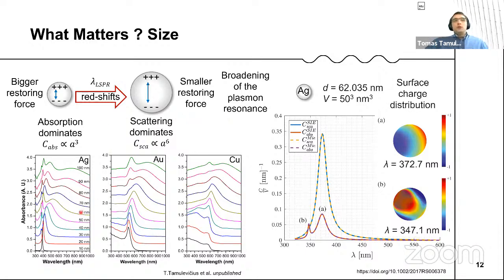And here are some numerical simulations with Mie theory for silver, gold, and copper. You will see why, because we had a small project about it. If we increase the size of the sphere, you can see that the dipole peak is shifting to longer wavelengths, and it's really broadening, as I just said. For gold, the resonance is in a different position because it has a different dielectric function. And for copper as well, it's slightly shifted, and copper has not so well expressed peaks because it has a slightly different structure.